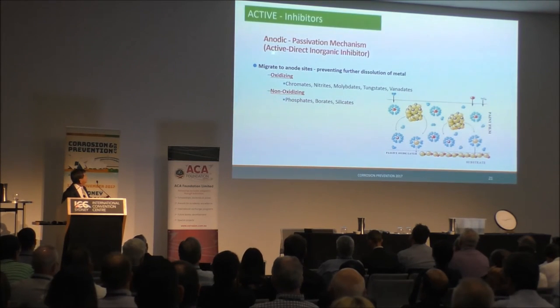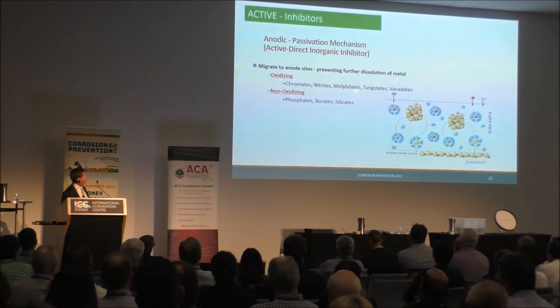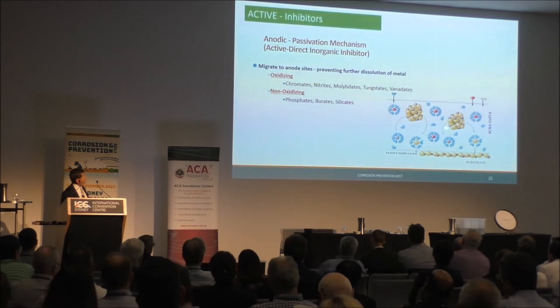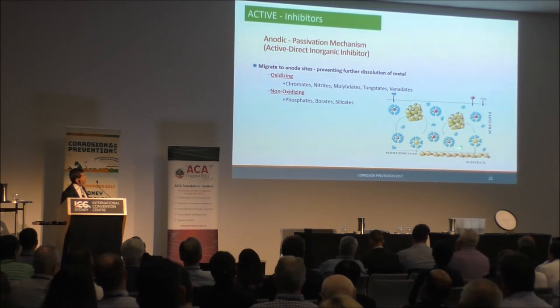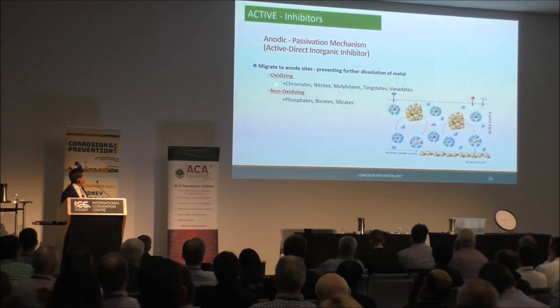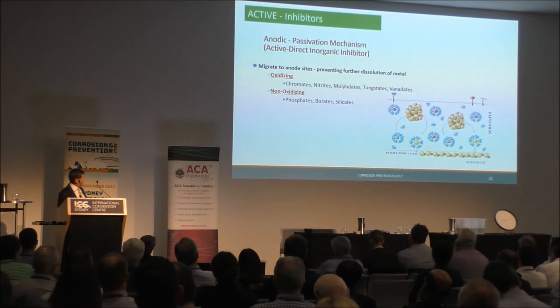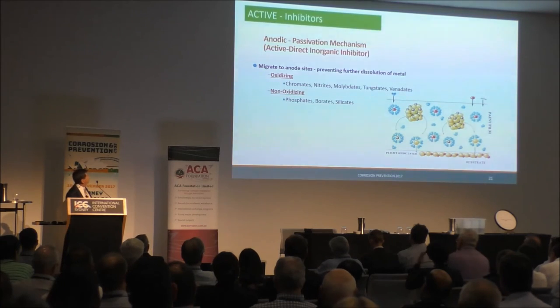Inhibitors, so as I mentioned, the anodic passivation type inhibitors, oxidizing anions like chromates, nitrites, and so on, these tend to be pigmented into a paint such that when the water transports through the paint, these relatively soluble, sparingly soluble materials can be dissolved and taken to the metal surface and cause a passive action often at the anodic sites. These oxidizing species and non-oxidizing species like phosphates and so on, if you could produce a mechanism whereby the surface is essentially passivated, then the corrosion rate slows down.